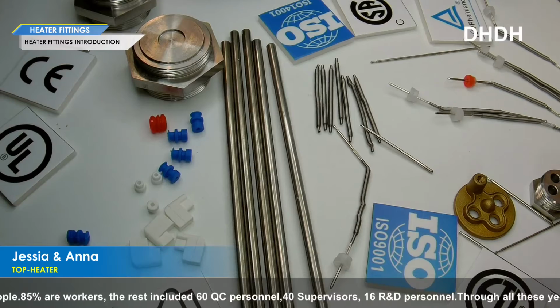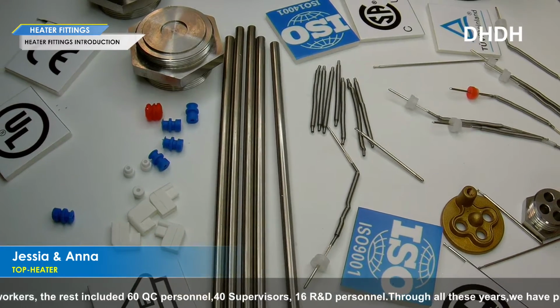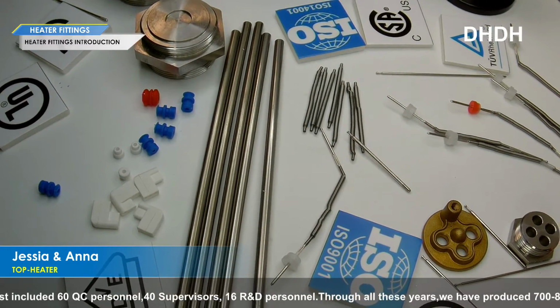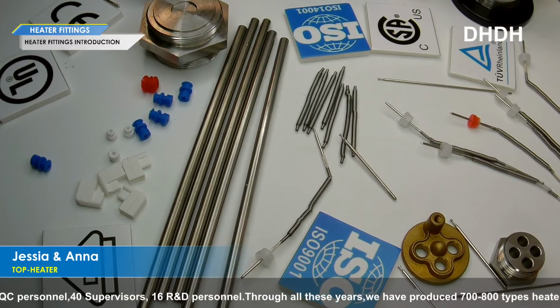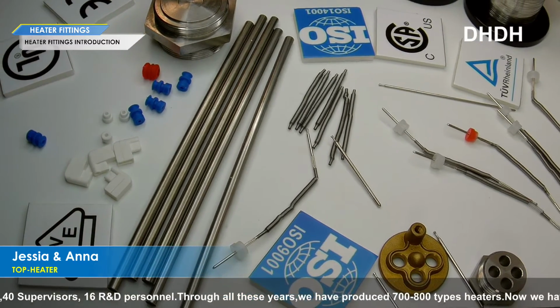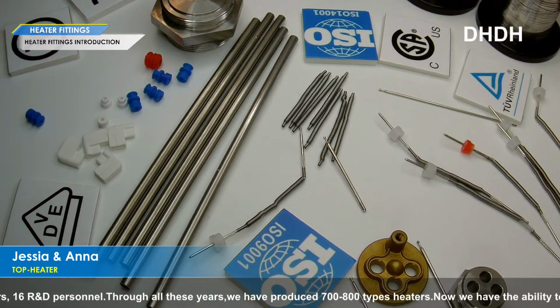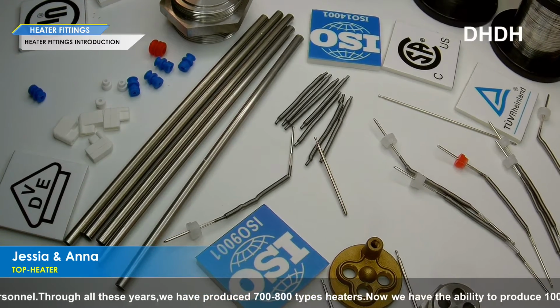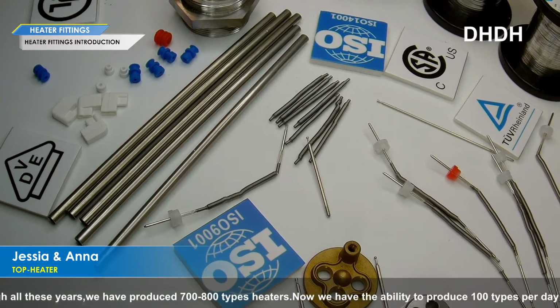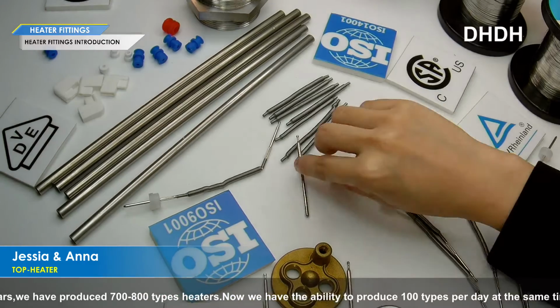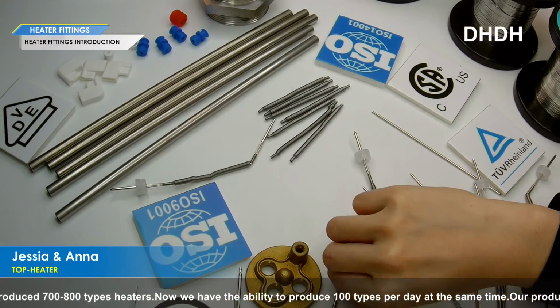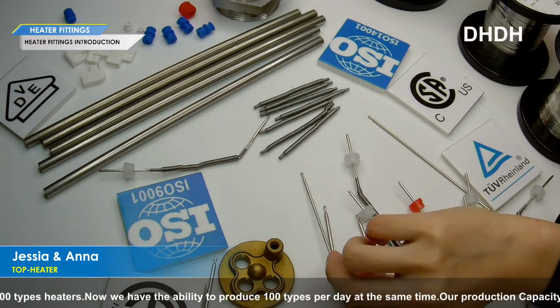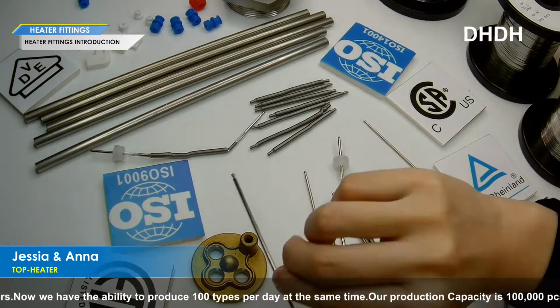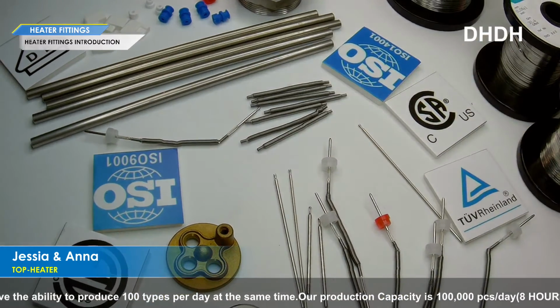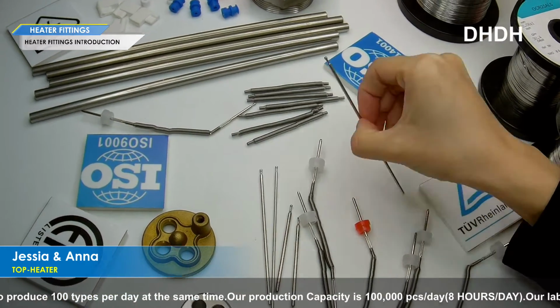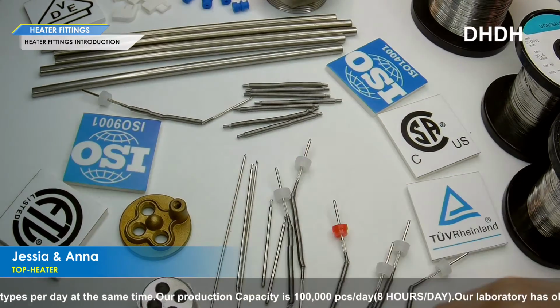And also before shipment, we will do the coating test, and we can check the thickness of the nickel coating, and we will do the bending test to see if it will peel when bending under different angles. Yes, and normally we also make the salt spray test, and it will test for 48 hours.